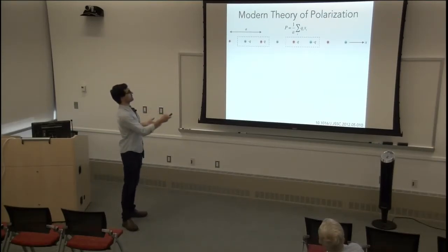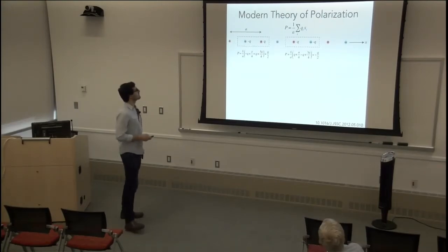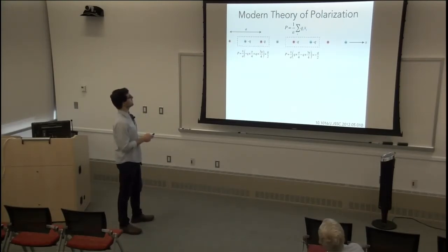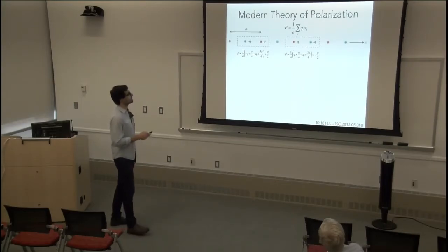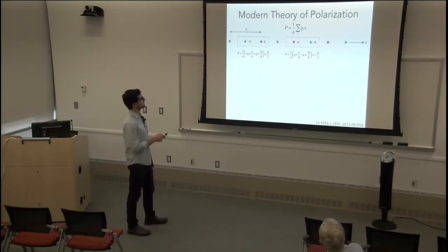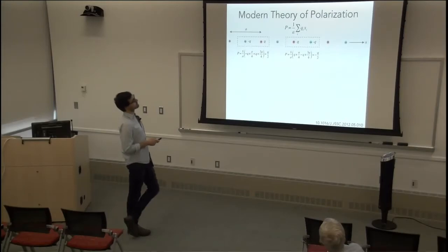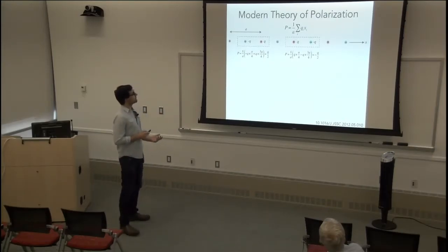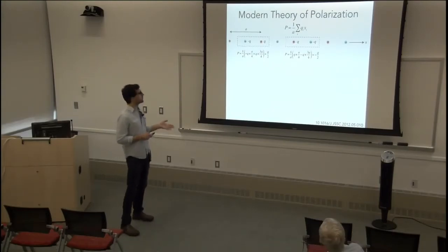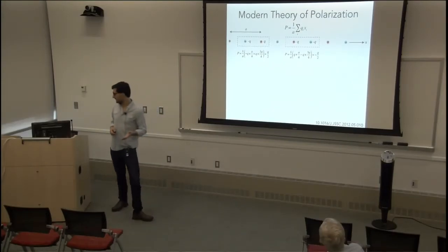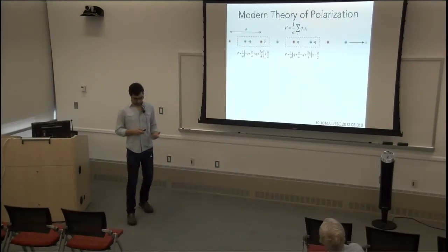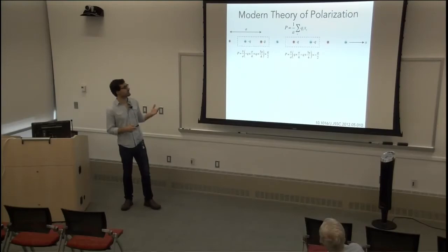So let's go together and calculate this quantity, P. Here it's 1 over A, and then you have negative Q times the position, A over 4, plus, because you're doing the sum, positive Q times 3A over 4. So you get Q over 2. Do the same thing for this one. You get Q times A over 4 minus, because you have a negative charge here, Q times 3A over 4. And you get minus Q over 2. So for basically the same system, you get two different polarization values. This is the big problem about polarization in infinite systems: it's not well defined.